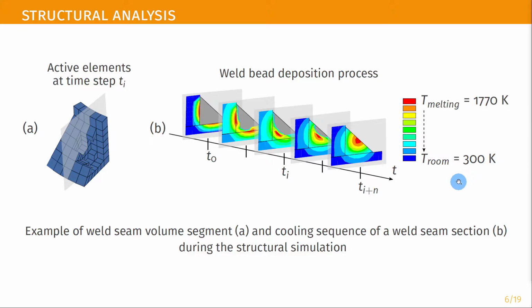The use of a constant initial temperature method in the thermal simulation poorly matched the classic approach of sequential activation of all the elements belonging to the element set. For this reason, a more representative simulation of the welding process from a structural point of view was implemented in this case. A correlation between element activation and element temperature is added.